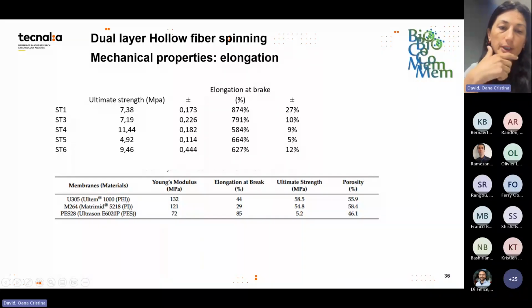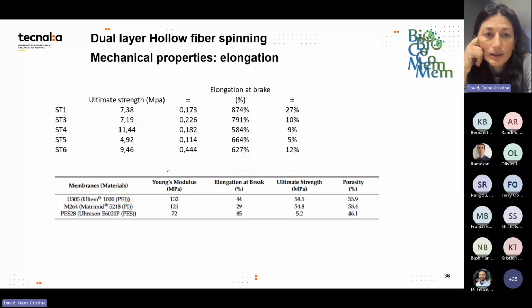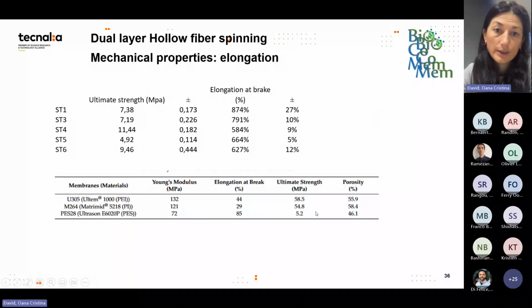We checked mechanical properties. We made elongation tests. And as you can see, elongation at break is very high. They are very, very flexible. So they are like a gum. It is much higher than the benchmark, which you can see here at the bottom. And then the ultimate strength is low. It's more or less comparable to polyethersulfone fibers.